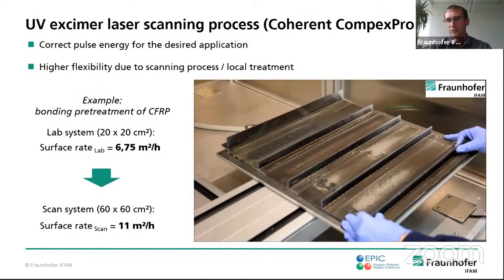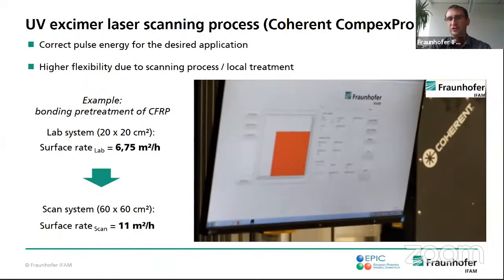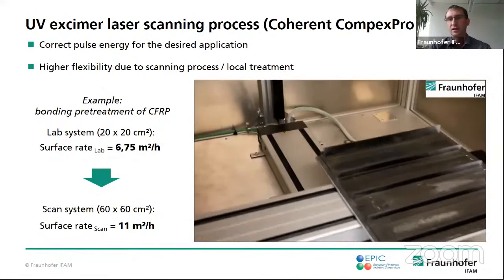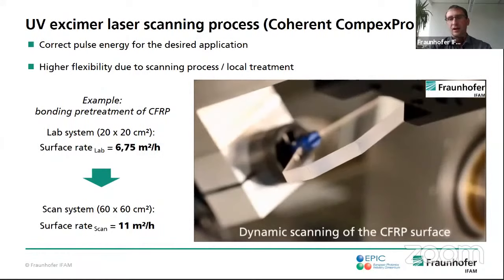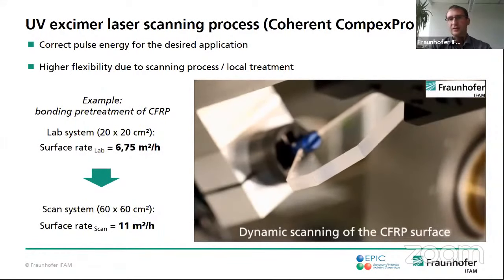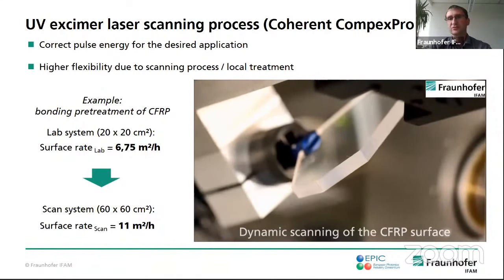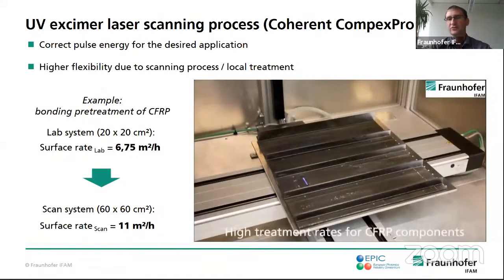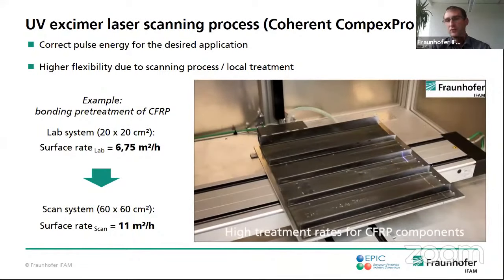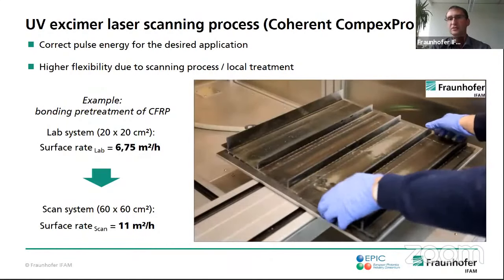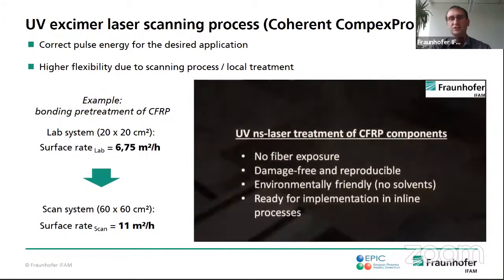And the main advantage here for the UV excimer laser treatment, you have a very high grade of absorption directly here in the epoxy resin material. But if you choose an excimer laser treatment for CFRP treatment, you have to choose the right amount of energy which you apply on the substrate. So if your energy is too high, you will remove the resin material completely around the fibers, and thereby in mechanical load, you will tear out the fibers from the material, and this leads to damaging.